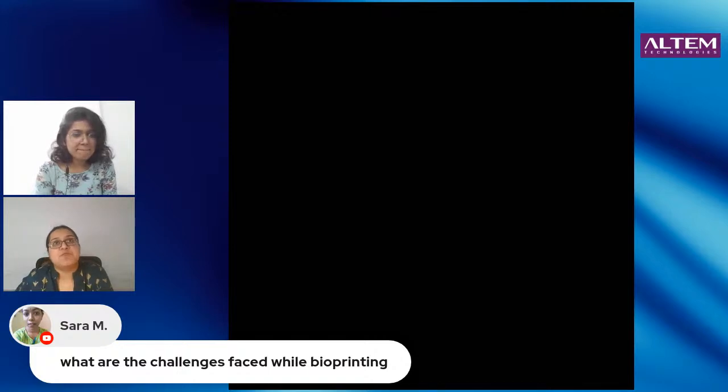The general challenges that we face, specifically here where I've used extrusion-based bioprinting, is that you have to get the microfibers. So you should have the correct viscosity of the bioink so that you can get that microfiber structure. The bioink composition is one of the major things that needs optimization and is also a challenge. And once you are set and you are able to get a microfiber structure, the next thing is how you adjust the printing temperature, the printing speed, and the flow rate. Those parameters need to be adjusted and optimized for the bioink.